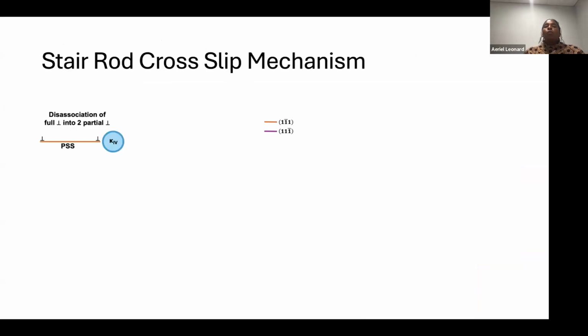So let's talk about why we might be getting stacking fault formation and twin formation. In general, when we think about cross-slip, we think, okay, if we have two partials, the only way they can cross-slip is if they recombine. They have to recombine into a full dislocation and then they can cross-slip. So that's just the traditional sense of the mechanism of cross-slip.